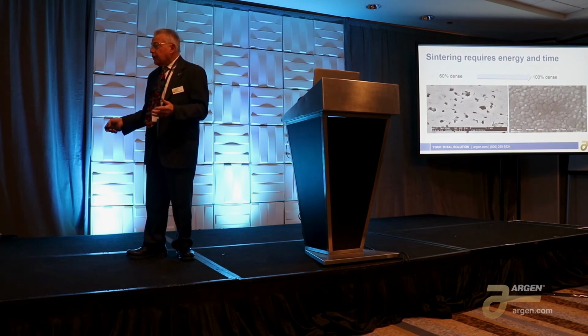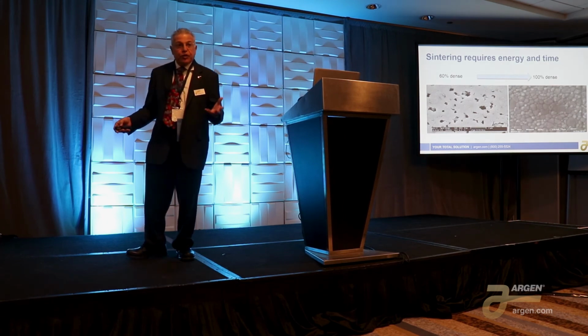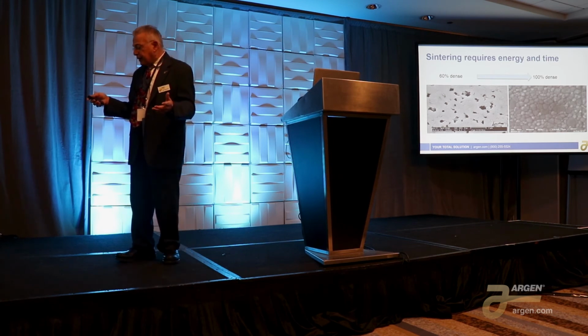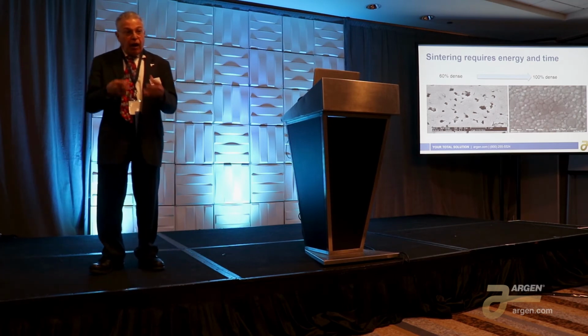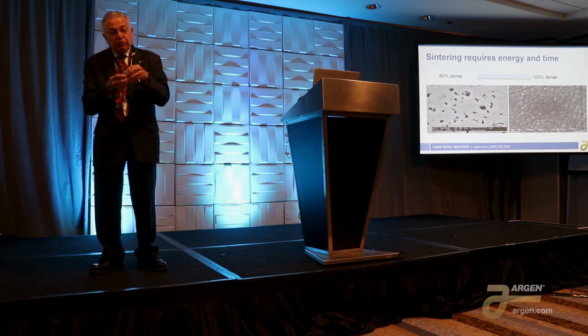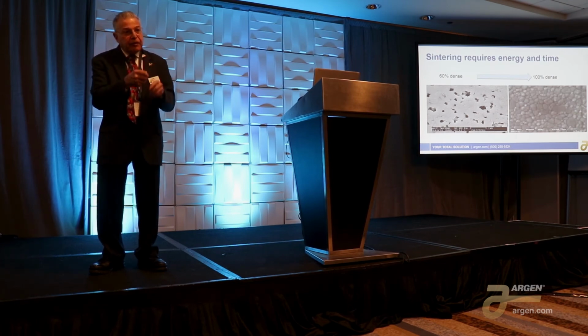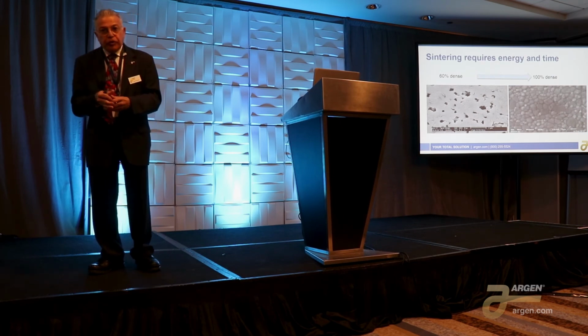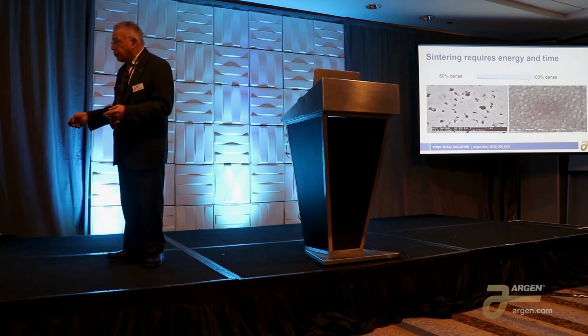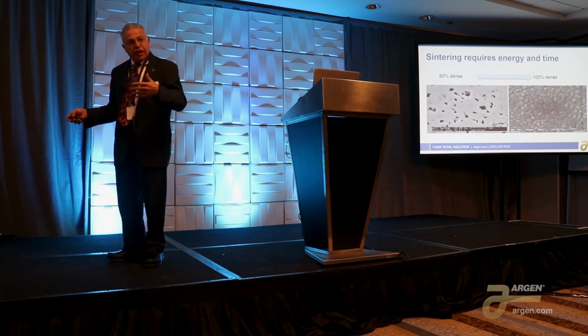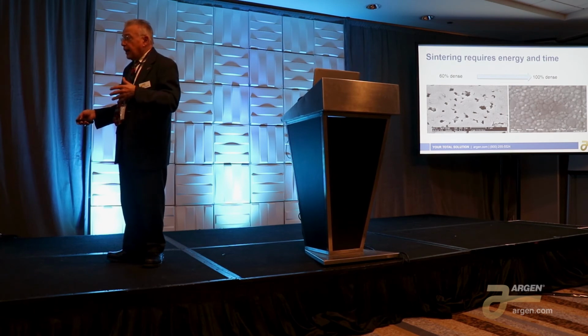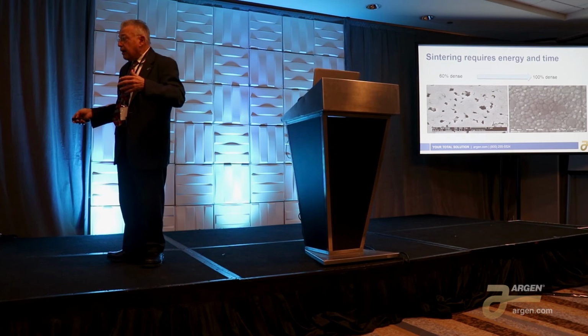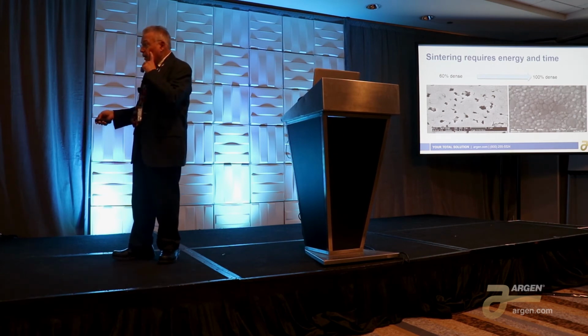So we're taking something that's 60% dense, which means it has 40% air in it. And I couldn't get a good picture of something at that rate, so this is like half sintered. This is only like 10 to 15% air. So air contains oxygen and nitrogen. And the oxygen molecule contains 2 oxygen atoms, and the nitrogen molecule contains 2 nitrogen atoms. Now we have to get that material out of this crystal. It's not like dental porcelain where it could evaporate. It has to go through the grain boundaries. That's the only way it's going to get out. So what do we have to have? Energy and time. Energy, because it has to have some excitation to move, and time, because you have to get it all out in order to get 100% dense.